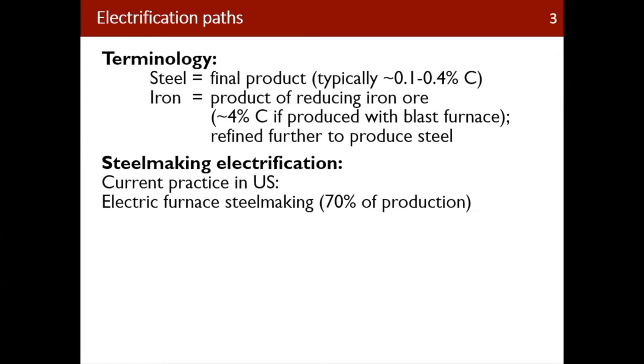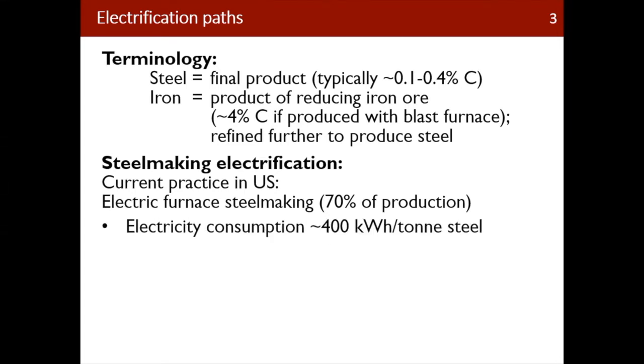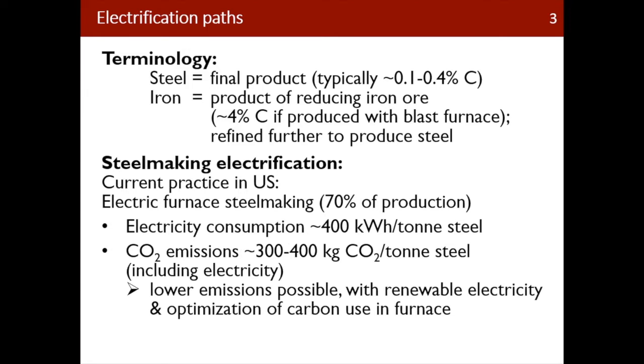And in terms of electrifying steel making, that's something we have largely done in the US already. So 70% of the production of steel in the US is by electric furnace steel making, taking largely scrap and recycling that, which does have a pretty small carbon footprint compared with blast furnace iron making. So the electricity consumption for North American electric arc furnaces is around 0.4 megawatt hours for a ton of steel. And the CO2 emissions are somewhere around 300 or so kilograms of CO2 per ton of steel.